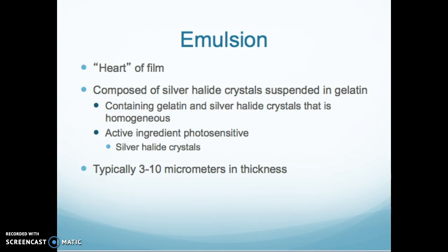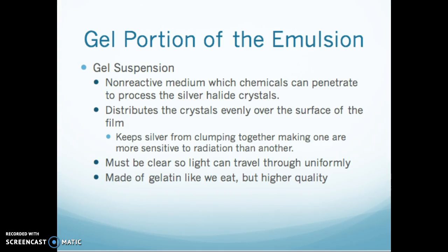The emulsion, so there's a lot to this. It's the heart of the film. It's composed of silver halide crystals, and they're suspended in the gelatin. So it's homogeneous, and the active ingredient is silver halide. Typically, it's between 3 to 10 micrometers in thickness. Now, one book says 3 to 5, the other book says 5 to 10, so we'll go from 3 to 10 on your quizzes.